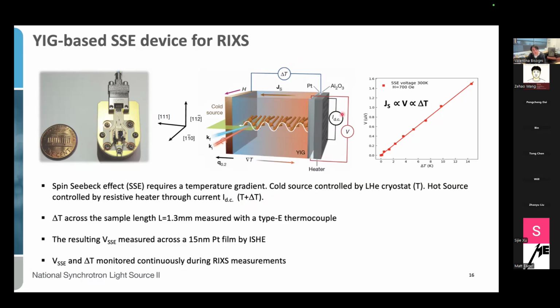Furthermore, to make sure that we really have magnon conductivity active in our device, we also deposited a platinum electrode on the side here, and we measure the Spin Seebeck voltage across this electrode. This is the result of our measurement at 300 Kelvin, where I'm plotting the Spin Seebeck voltage as a function of delta T, the temperature difference across the crystal, and you can see that we have this linear behavior of the Spin Seebeck voltage as we increase the temperature difference across our crystal, which means that the magnon current is increasing as we increase the temperature gradient.